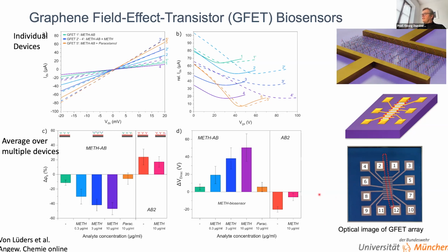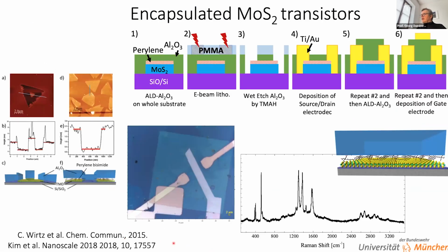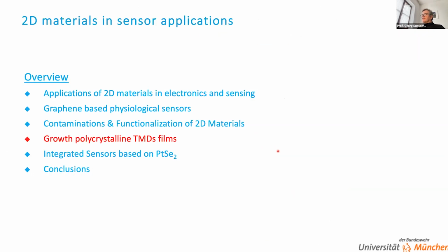I'm not saying that other routes are not also successful, but we gain now very consistent results, and we believe that we can functionalize now with also other antibodies. Just as a side note, we had shown that this perylene functionalization also works on MoS2. Here we used it as a passivation layer to then attach Al2O3. Here is a MoS2 FET, which is buried in a perylene layer with aluminum oxide grown passivation layers on top, shown like this. What I'm trying to say here is that the chemistries on the MoS2 surface and the graphene surface with regard to these perylene molecules seem to work very consistently and similarly.